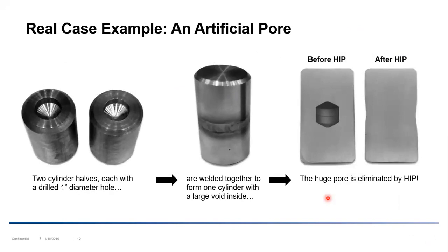And here I want to show an example of what the hip process can do. So these are showpieces that were made to show the effect of hipping. On the left here, we have two steel halves, and we have drilled a hole in each of those. Those ends are put together and welded together, creating a cylinder with a big void inside. And then these specimens were hipped, and we can see the results here to the right. These are cross sections of those samples, and the sample on the left here is a reference, so this has not been hipped, and we can see this big void inside this half cylinder. The specimen on the right was exactly the same specimen, but then it was hipped. And as we can see, we were able to eliminate this huge pore with the hip process. And since the pore is relatively large towards the sample size, we can see that we also get some macro deformations on the sides here.